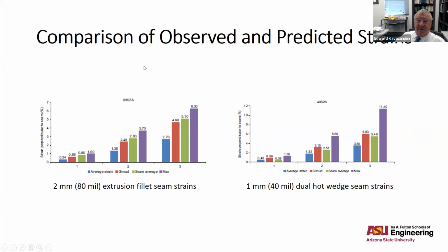How do those results compare to what Giroux's equations were predicting? Well, here are three different strain levels. Here's the extrusion fillet seam, those big blobs of resin. At low strains, this was the average strain in the geomembrane. This is what the Giroux equation would predict for the strain concentration.